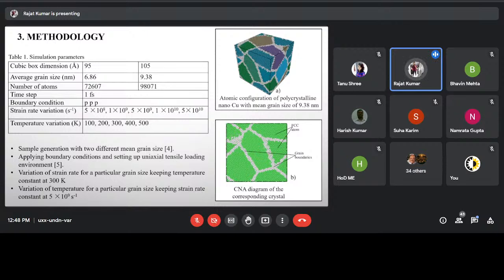And then after the generation of the sample, the first step is to apply the boundary conditions. The boundary conditions help us analyze the metal so that when we are simulating the real environment, after each stage our atoms should not be lost from the environment. So in order to keep the number of atoms constant, we apply boundary conditions. After that, the EAM, or embedded atom method, potential is used to describe the interaction among atoms by using Newton's second law of motion.